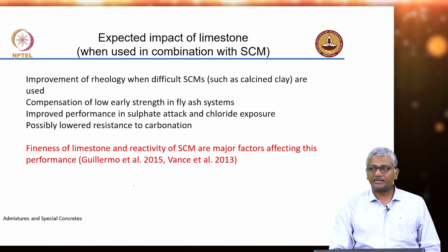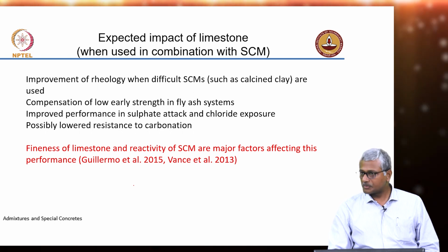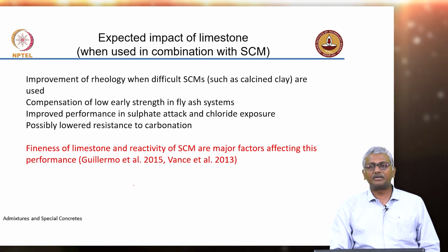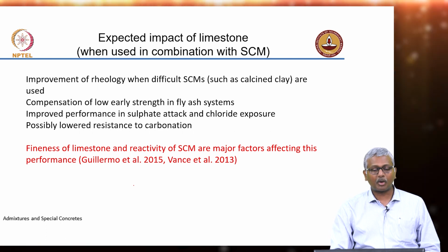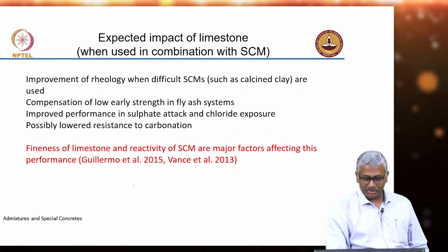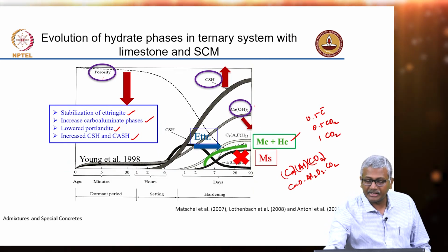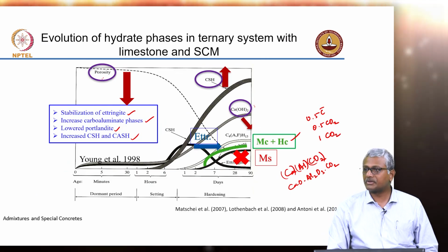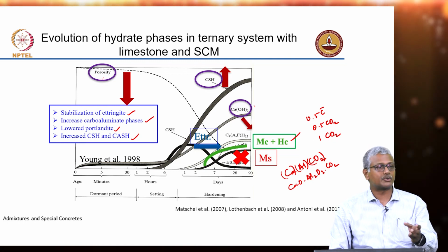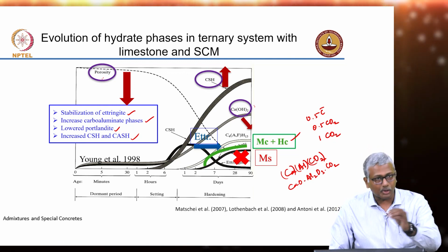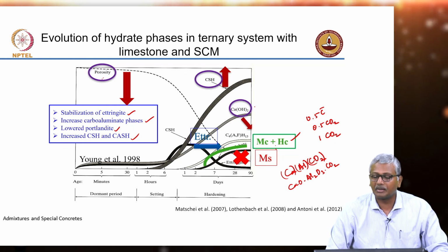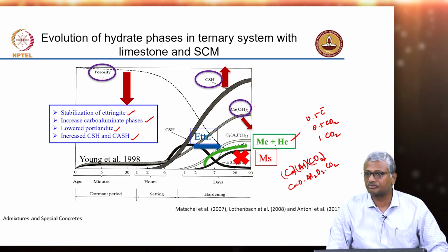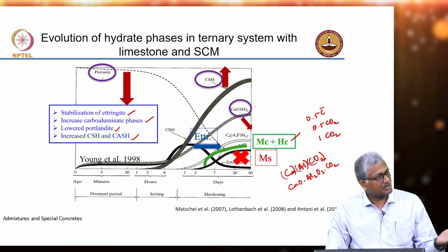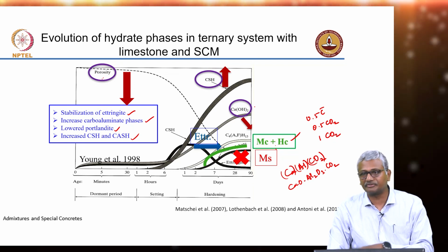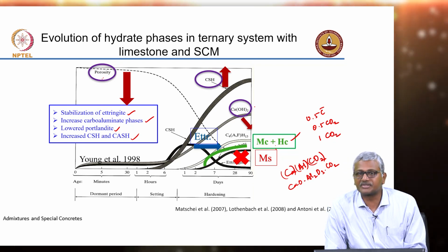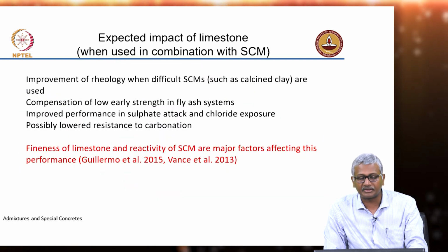Alumina is there, it will bind the chloride. So in chloride exposure your durability will also improve, but the problem will be the resistance to carbonation, because you are cutting down your calcium hydroxide significantly. Calcium hydroxide was earlier used only for the pozzolanic reaction. Now it is also used to form monocarbonate and hemicarbonate. The reaction of limestone with alumina has to happen in the presence of calcium hydroxide to produce these carbo-aluminate phases, which I will show you in just a minute.